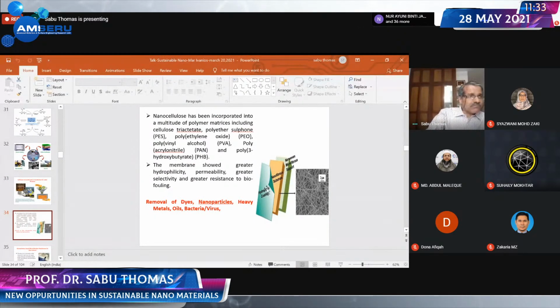We worked on a membrane which has 3 layers. The bottommost layer is polyacrylonitrile. Just above that, we have electrospun PVDF. On the top of this, we have made a coating with nanocellulose dispersion. This is hydrophilic. And if you have such a membrane, you can remove dyes, you can remove nanoparticles, you can remove heavy metals, you can remove oil, you can remove bacteria, you can remove viruses.